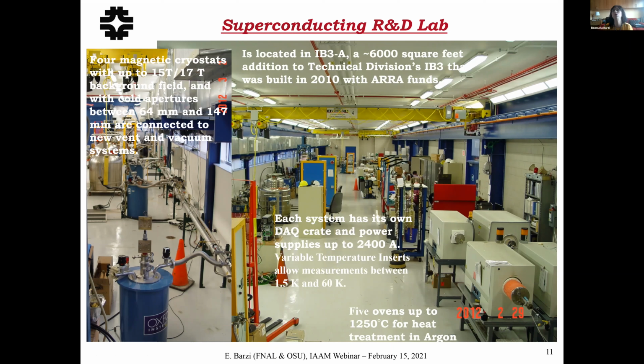That's where we do our temperature variable experiments. These are the ovens where we do our heat treatments of low temperature superconductors in inert argon atmosphere or in oxygen atmosphere. This is Bi-2212, for instance, a high temperature superconductor. You need to heat treat it in oxygen to form the superconductor, and sometimes even under very high pressure. So anyway, and this is the rest of the lab. Here are a lot of the setups that we designed.